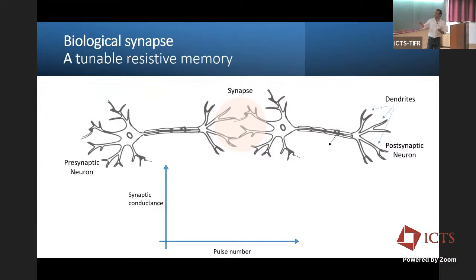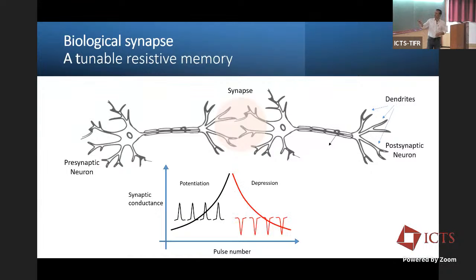Suppose there's a problem, and for some reason this neuron is firing first, which you don't want, then you want to make this synapse non-conducting, and hence you want its electrical conductivity to go down. So if this neuron gives you the first pulse, then you can continuously get that, and you want this synapse conductivity to be large. But if this neuron fires first, you get opposite pulses and the conductivity goes down. So effectively, a synapse is like a resistive memory, where continuous pulses in a single direction increase the conductivity, and the opposite pulse direction decreases the conductivity, which is called a depression.